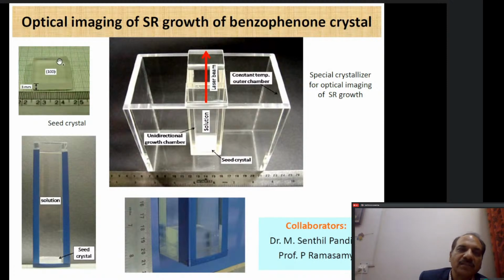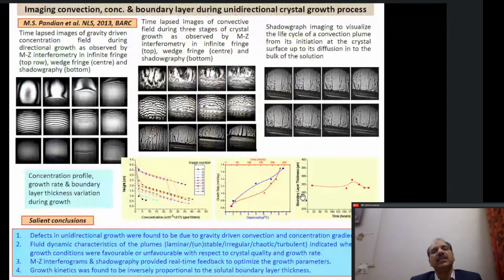And this is the seed crystal. This is a benzophenone crystal, 100 seed crystal. This was of 1 inch by 1 inch dimension, and this cell was also 1 inch by 1 inch, but 7 inches long. 1 inch by 1 inch X and Y, and Z was 7 inches. So we put the seed crystal at the bottom of this, then we filled up this with a solution, and these are the results which we obtained using our shadowgraphy, Mach-Zehnder interferometry, and we were very comprehensively able